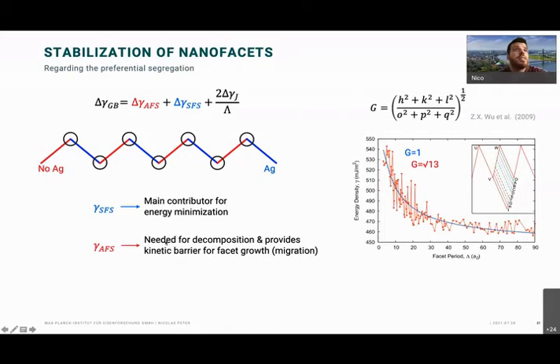Okay, anyways, so this is maybe the point here that is needed for the decomposition, as I said, and acts as a kinetic barrier. And you can see here on the graph, this is some simulation work from previous people, and it shows the blue curve, the dotted curve is if you have a G factor, which is a purely geometric thing and is 1 for the symmetric boundary, the 210 boundary, which says this is 210, this is 210, so this gives a normal number. It's a very smooth decrease, so the facet period wants to increase, so you want to form a very long boundary. If this is now an irrational number, like square root of 13, which is the case for us here, it becomes very jerky. And that means it comes to very high energy barriers locally, which act then as the kinetic barrier. And the junctions are negligible here due to the kinetic barriers that we actually observe.